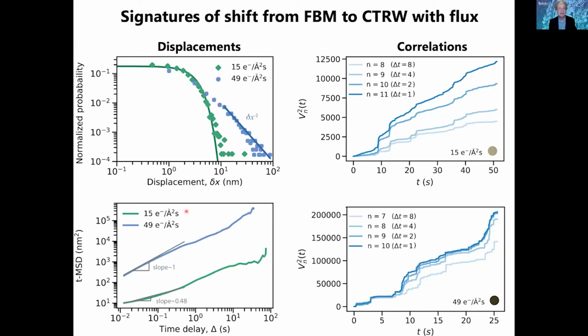We can verify that by looking carefully at a number of detailed characteristics of these trajectories. For example, we can look at how the mean square displacement changes as a function of time, or we can look at the distribution of displacements. This green curve here is a Gaussian distribution. And you can see that even at low fluxes, there is a deviation from a Gaussian, which is consistent with the fractional Brownian motion. But at the high dose rates, we see this heavy-tailed distribution. It's not Gaussian at all, consistent with continuous time random walk.